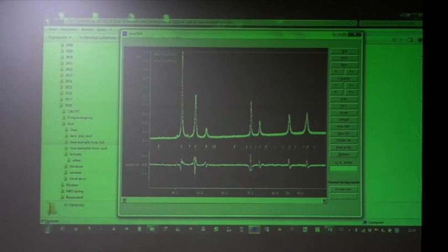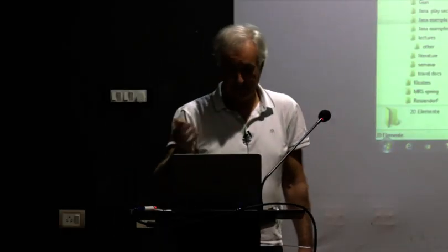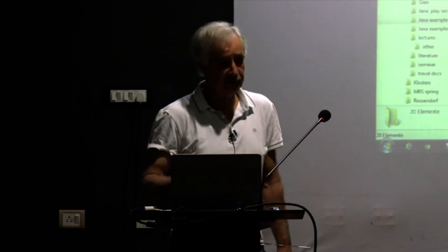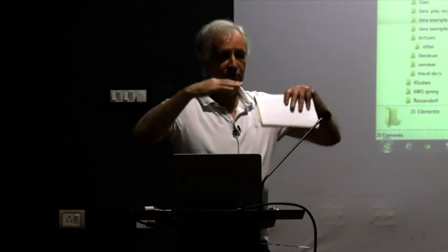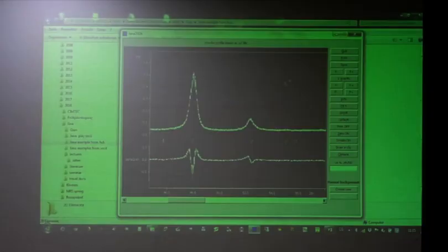And if you enlarge any one of these peaks around here, you see that the fits are not too bad, actually. They're shifted a little bit in their positions, which means that maybe the zero of our instrument is not exactly zero. There are some shifts. So let's quit.